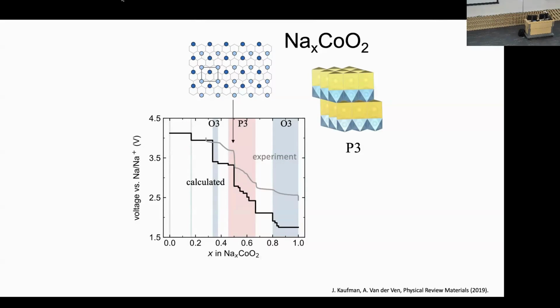This is all for sulfides. For oxides, oxides tend to be more ionic. So the interactions of the sodium ions are much stronger in these layers. And you can see that in the voltage curve as well. You get large steps and very complicated structures in the voltage curve. This is calculated, and then this is experimental.